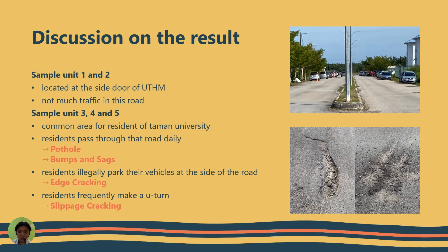Residents of Taman University apartment and Paris Haus are bound to pass through that road daily, so after a certain time this causes potholes, bumps, and settlement. Due to the deficiency of parking inside Taman University apartment, residents tend to park their vehicles outside at the side of the road, causing edge cracking of the pavement. Additionally, residents frequently make U-turns, which causes slippage cracking over a period of time.